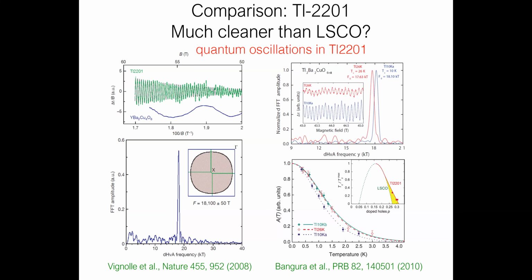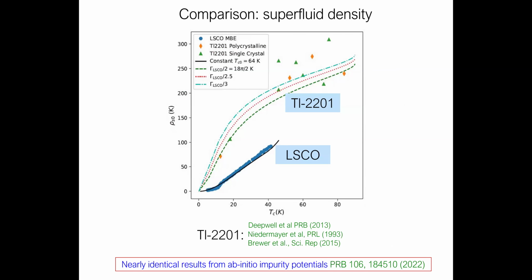So do we see a difference? Can we see that there's disorder playing a role here? And to make a rather long story short, when we did these calculations for both systems, again, taking the electronic structure from angle resolved photo emission in both cases, we found that you could fit the thallium data. It's much more dispersive than the LSCO data, but those are thallium crystals, which are notoriously hard to grow. So let's take this overall trend as being real. And then the message was that it's basically the same physics.